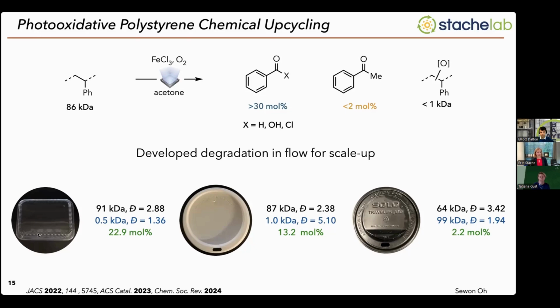And so what he found is that if you have a near pure polystyrene product like this clear lid, the process works with about the same efficiency. But as you start to move on to more complicated materials that are multi-material products, may have inorganic composites or other dyes, we do see a drop off in efficiency. And you can see with this black coffee cup lid, we see the efficiency drop off to almost no reaction. And so for one, this highlights the limitations of using photooxidative degradation to convert polystyrene into benzoic acid.